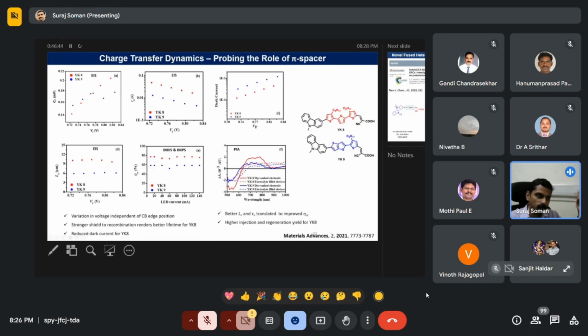spacer to YK8 and YK9, here the capacitance, this is an electrochemical impedance measurement where you change the frequencies and you scan over a range of potential, and you see how the electrons are being populated into your semiconductor. So that will give you your capacitance. So in both the systems, your capacitance is more or less the same. So that means your conduction band is the same for YK8 and YK9.